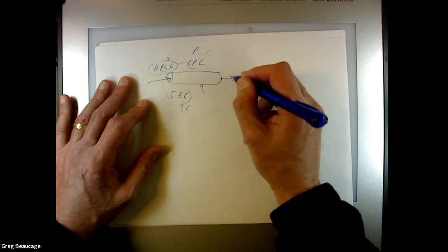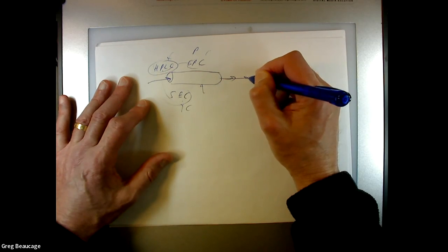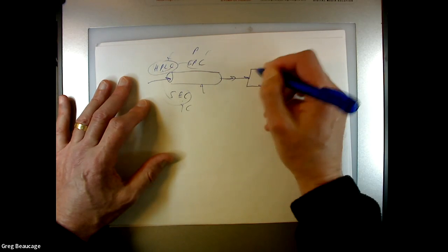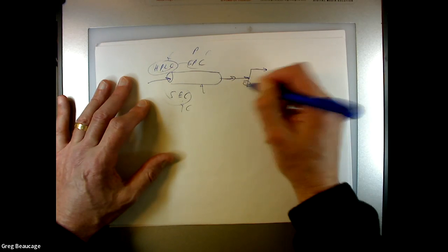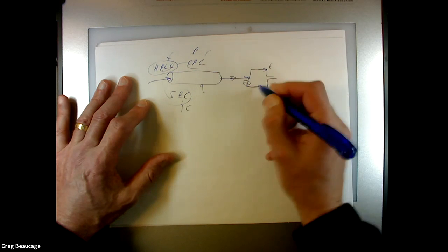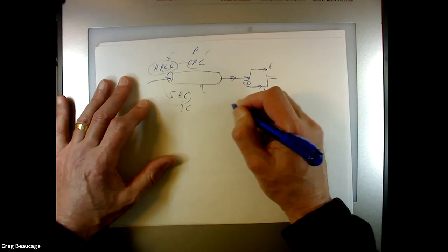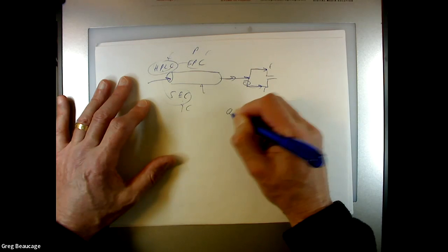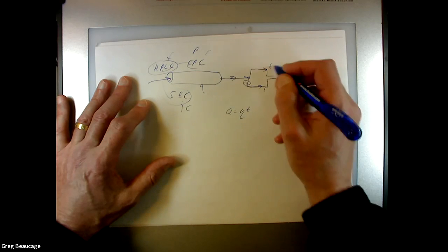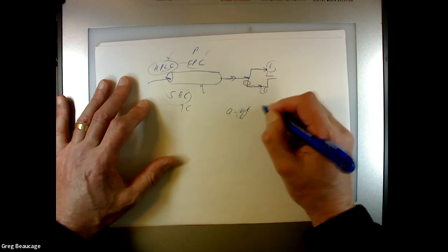Anyway, you separate that out, and then it comes over here, and you run it through. I forget the name of it, but it's an equivalent of a Wheatstone bridge. So you run your sample, and you have a solvent pool here, so you compare the time that it takes to go through the 2 things. The flow rate coming out of this is going to be proportional to viscosity times the time. If you measure the time, you can get the viscosity from it. This is kind of Stokes' law.